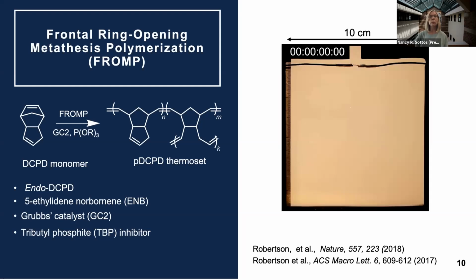But what these inhibitors do in working with this monomer is that we're able to move from the test tube, from a very small volume and doing frontal polymerization on a very small scale, to larger molds. And here I just show a casting mold of our dicyclopentadiene monomer. The heat trigger here is a resistive wire, and it's just on for less than a second, actually. And you can see, again, a smooth polymerization front progressing throughout the mold. And what we wind up with is a thermosetting polymer, polydicyclopentadiene, by the time all the monomer converts.